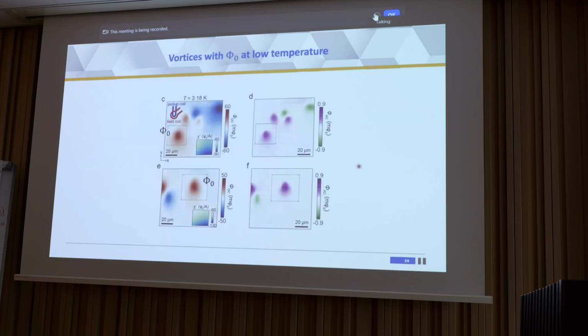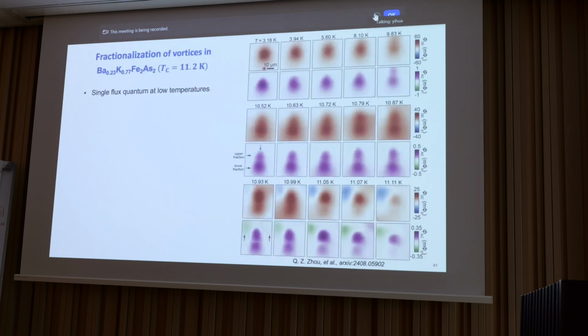Then we measured other vortices, which seem to have a flux value integrated to Phi naught. However, as we increase the temperature, we can see that they are deforming, as you can see from these rows in the AC flux images. Around 10.52 Kelvin, you can see that it splits apart into two fractions, the upper and the lower part. And the upper part becomes stronger and stronger as the temperature increases further. At around 10.93 Kelvin, the two parts have almost equal intensity. And as you go higher, the top part becomes stronger, while the lower part is weaker.